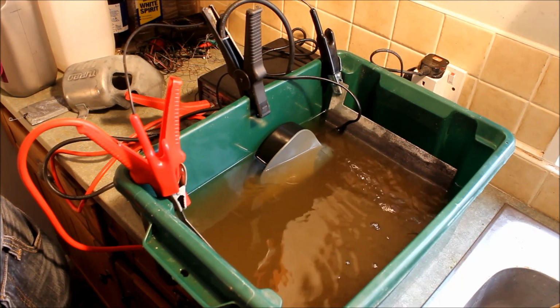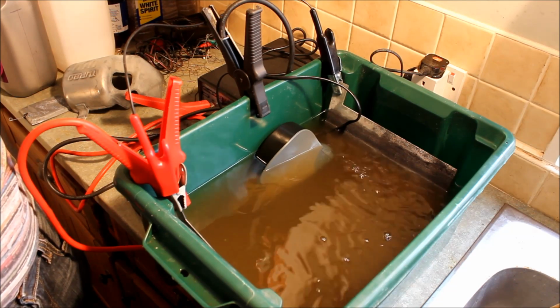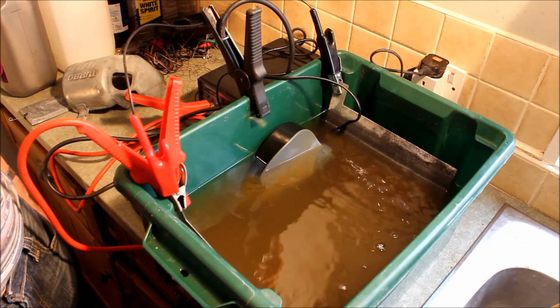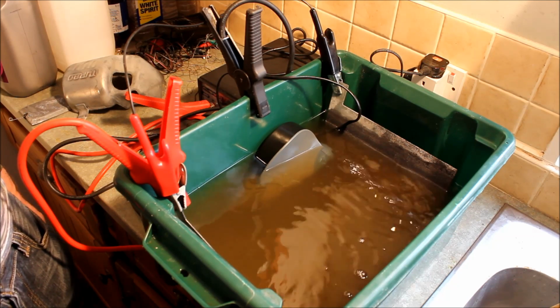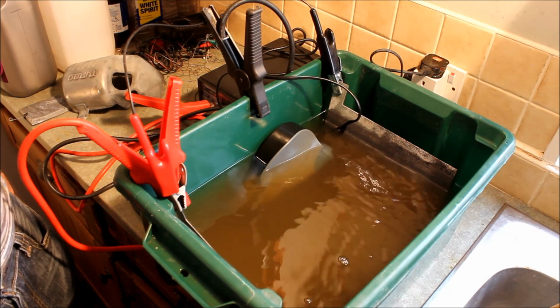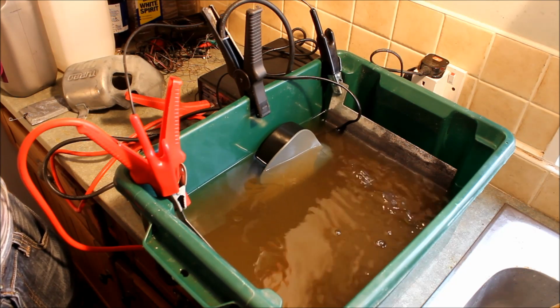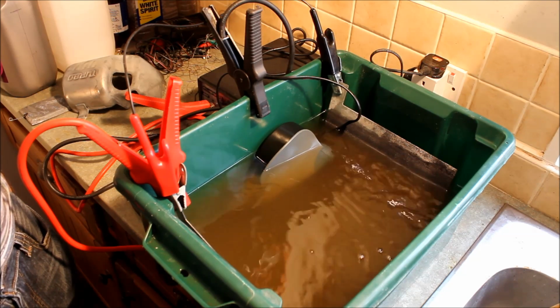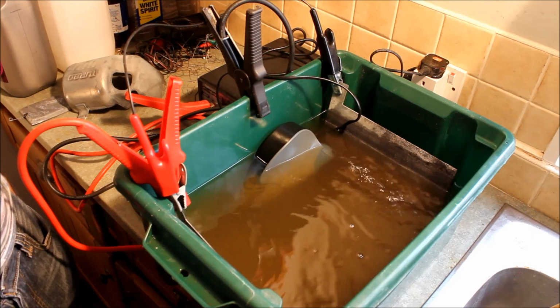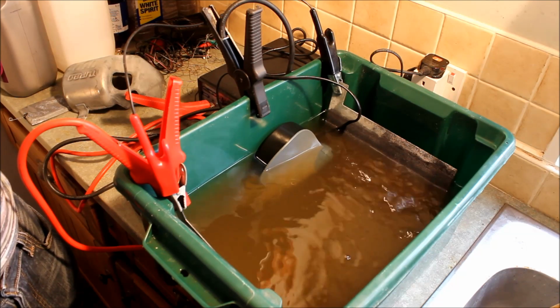Finally though, you may just find that none of that stuff works, and the only thing you can do then is drop the current and increase the plating time. And that's just a linear relationship. If you halve the current, you need to double the plating time to get the same thickness. If you go for a quarter of the current, then you'll need to quadruple the plating time to get the same thickness.